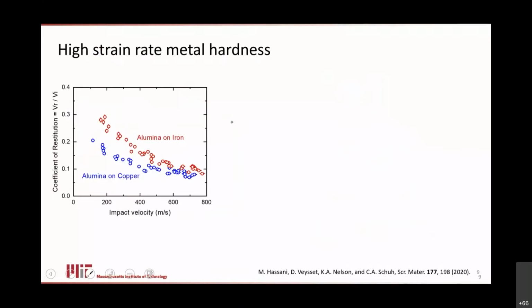Also, like nanoindentation, this test platform is a really high throughput apparatus. So when we go to test the properties of copper, like I just showed you, we don't just do one of these tests. With the same tiny little sample and a handful of alumina powders, we can repeat the same test over and over and over and get dozens of data points. And we can even vary the impact velocity so as to assemble a response curve like the one shown here. I'm showing the coefficient of restitution. That would be the outbound velocity divided by the inbound velocity.